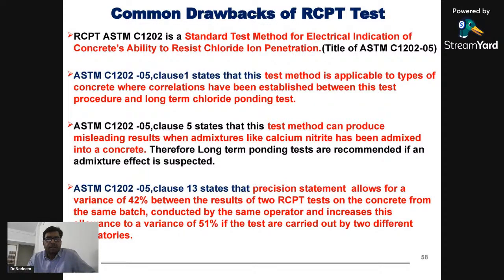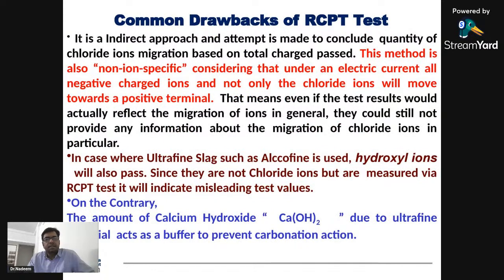Another thing is that their precision statement allows for a variance of 42%. So even for results of the same batch of concrete from the same laboratory, a variance of 42% is acceptable. And if that sample is tested in another laboratory, a variance of 51% is allowed. So these are the drawbacks of this test, unless it is tested with a correlation. These are the various drawbacks of this test.